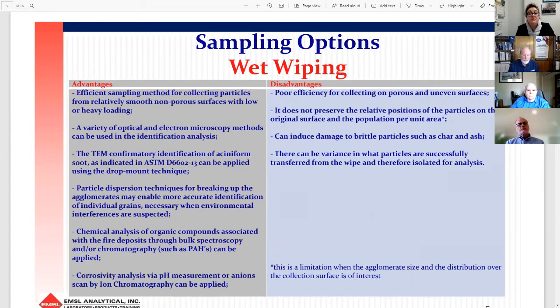It is good for relatively smooth, non-porous surfaces with low and heavy loading. You can apply a variety of methods when you need optical, electron. You can run the TEM if you need soot. If you found soot in the sample and you want to know why it is there, how it is really soot, you can apply that type of analysis. We can run the chemical analysis as GCMS for PAHs, metals, whatever is needed for a more comprehensive project.